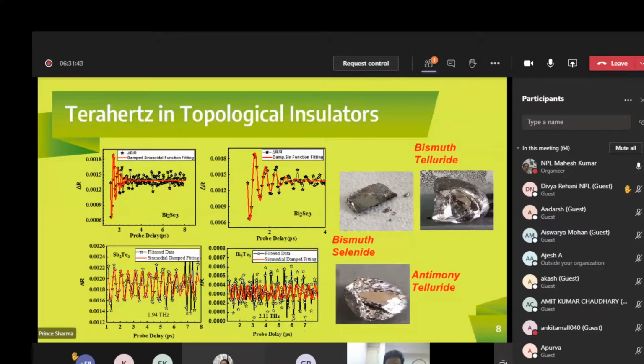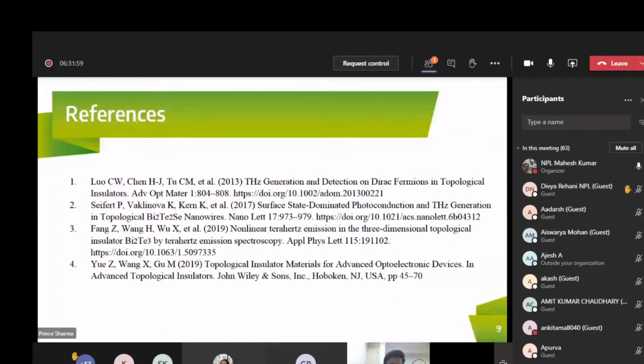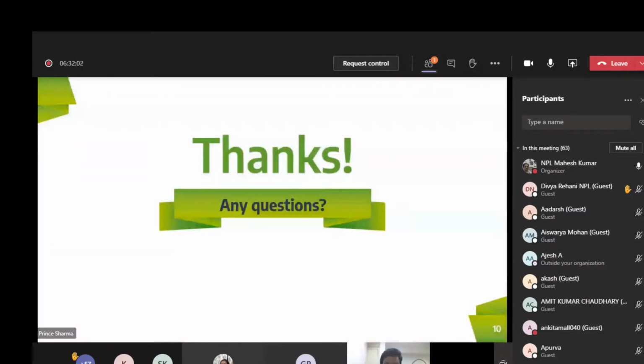The terahertz frequencies that come out through these oscillations are 2.11 terahertz in case of bismuth telluride, 2.42 terahertz in case of bismuth selenide, and in case of antimony telluride it is 1.94 terahertz. These are a few references, and thank you.